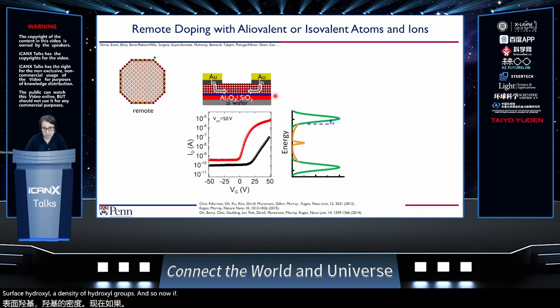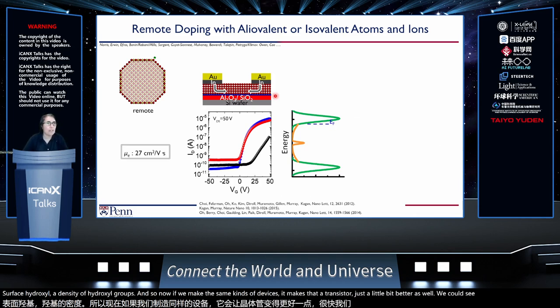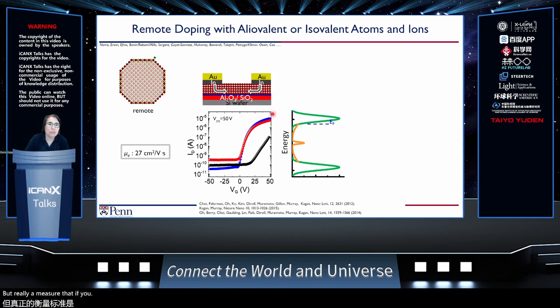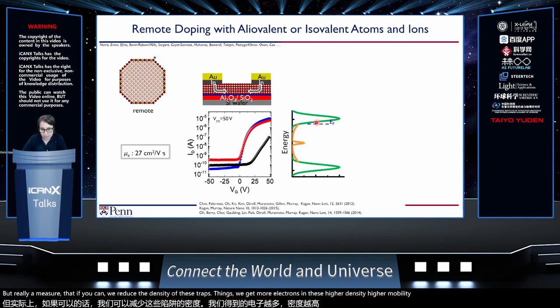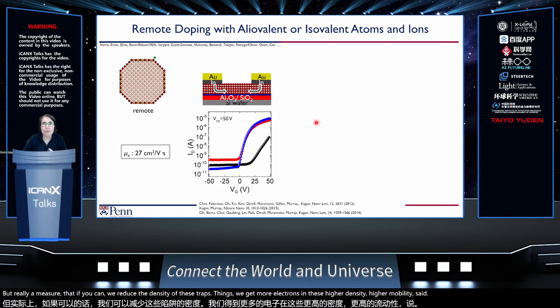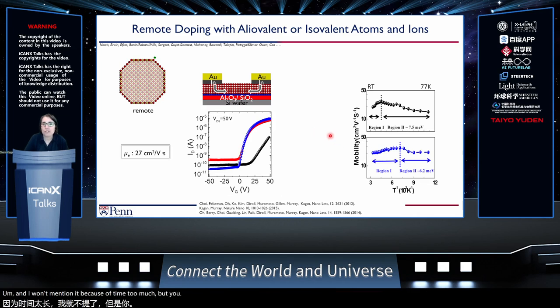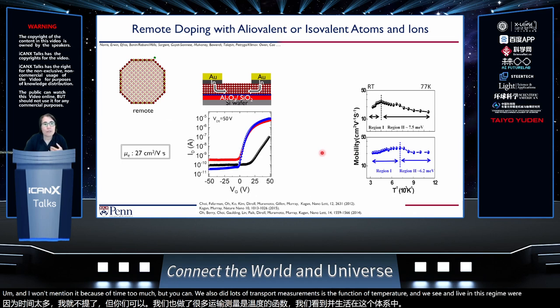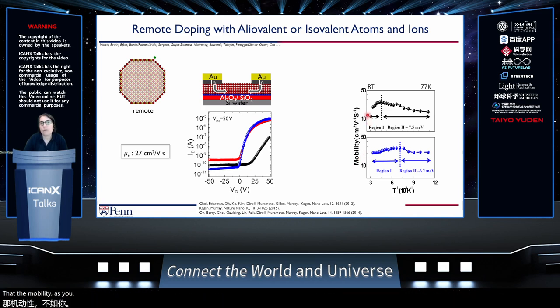And so now if we make the same kinds of devices, it makes the transistor just a little bit better as well. We could see mobilities then at the time of about 27 centimeters squared per volt second, but really a measure that if we reduce the density of these trap states, we get more electrons in these higher density, higher mobility states. And I won't mention it too much because of time, but we also did lots of transport measurements as a function of temperature. We live in this regime where people refer to it as band-like transport, the idea that the mobility increases as you go to lower temperature and it's not thermally activated like you'd anticipate for a hopping mechanism.